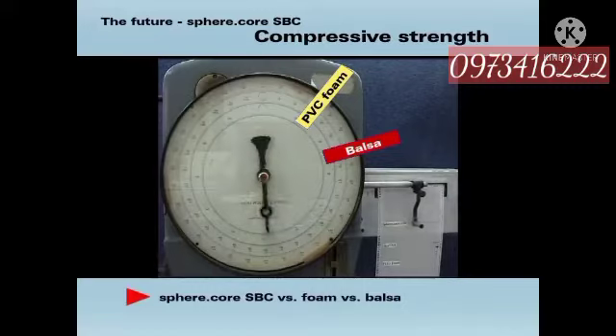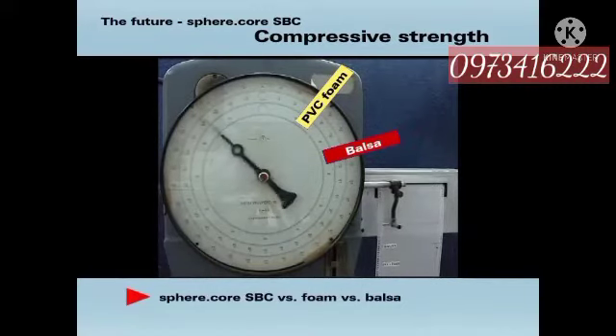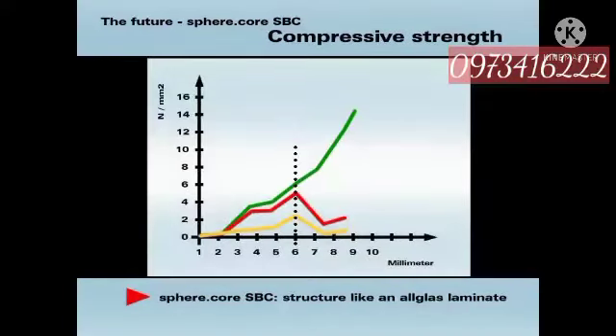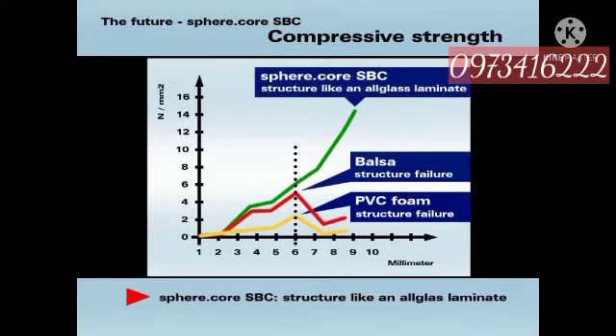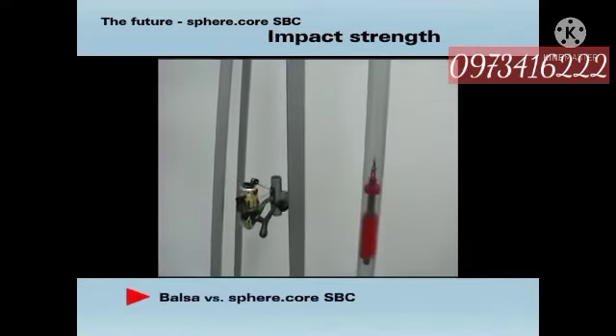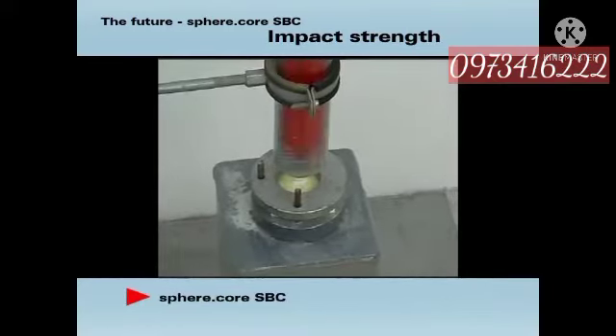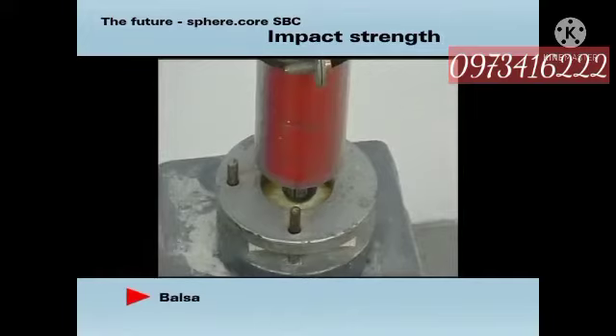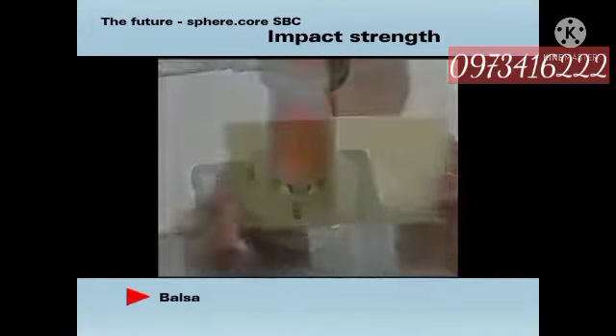The superiority of a sphere core SBC laminate becomes especially clear by comparing the compressive strength with classic core materials. The test shows that unlike the behavior of foam, balsa, or honeycomb, the compression properties of sphere core SBC are of the same character as those of an all-glass laminate. A characteristic difference to the behavior of classic core materials can be found by testing the impact strength. It shows that the material combination of high modulus fibers and the elasticity of microballoons gives sphere core SBC extreme energy absorbing properties.